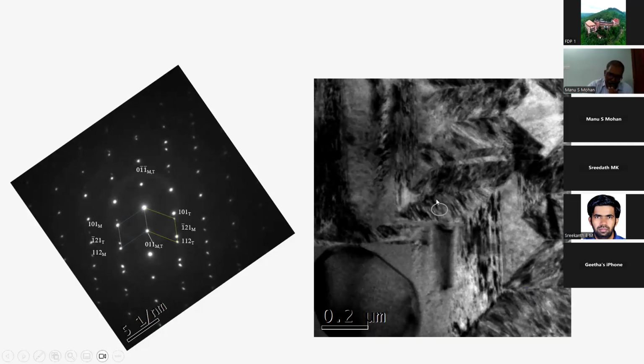So now two things you observe here. One is, this is 0.2 microns. Each of these parallel lines you see here, these are twins actually, and their spacing is 5 nanometers. You imagine 5 nanometers, which is around 50 angstroms, if I'm right. One aluminum unit cell itself is 4 angstrom, so around 40 aluminum unit cells can be kept in this.